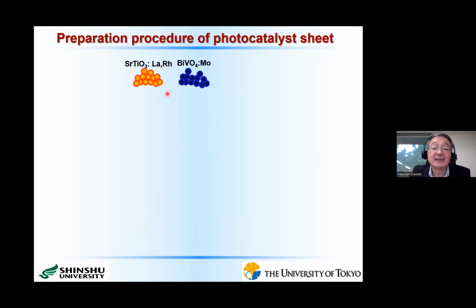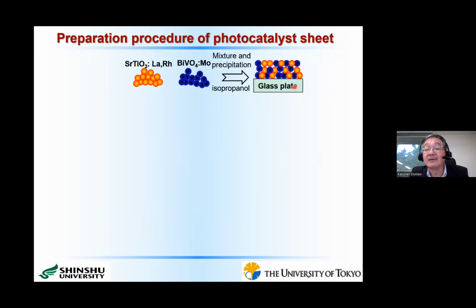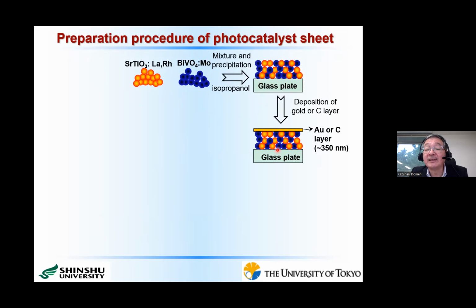Here I show the preparation procedure of our photocatalyst sheet. We mix these two particulate photocatalysts in an isopropanol solution, then drop cast on a glass plate and dry. Then we can get this kind of mixed powder layer. The thickness is at most about 10 micrometers. After that, we deposit a conducting layer by sputtering or evaporation. In this case, gold or carbon, like this one.